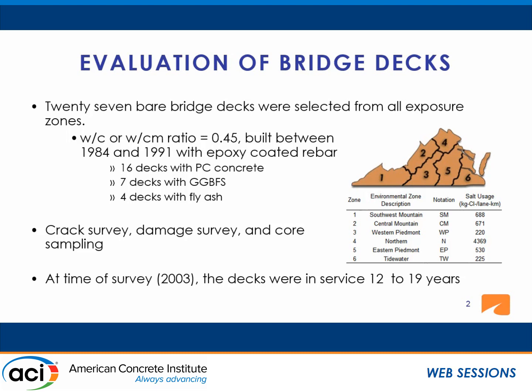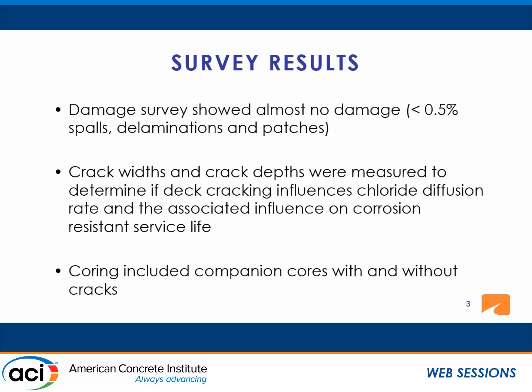The evaluations included the crack survey, damage survey, and coring. The damage survey showed pretty much no to really low amount of damage, which includes the spalls, delaminations, and patches in all of these decks. In the field, crack widths were measured, and in the lab, on the cores we took from the field, we measured the crack depths. In order to compare the influence of cracks on the chloride diffusion, we took companion cores. We have one core from a crack location, and then right next to it, we take a core on a solid concrete. So we can do a one-to-one comparison.